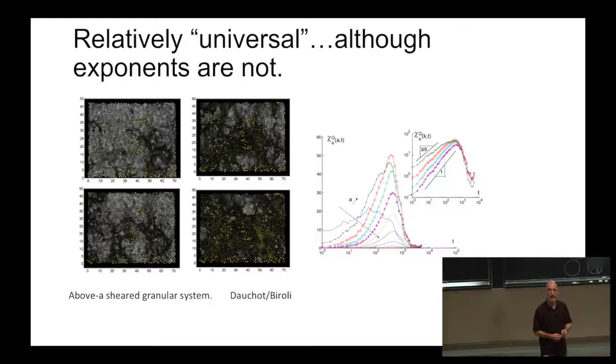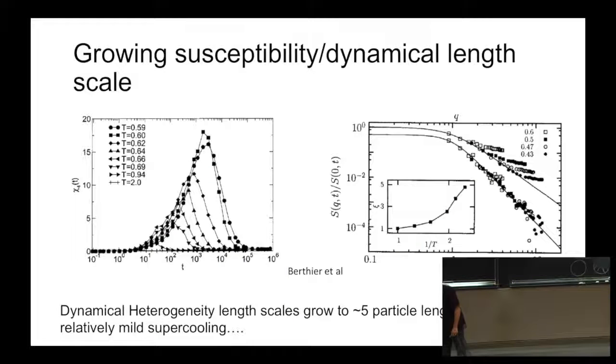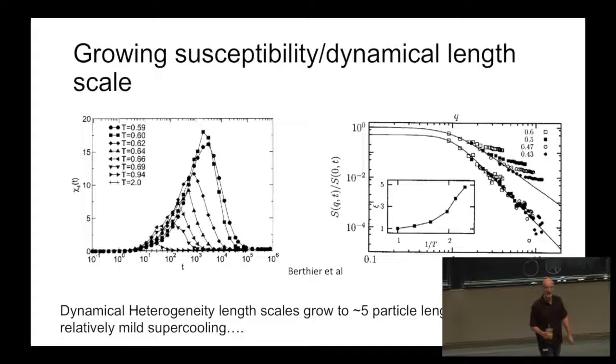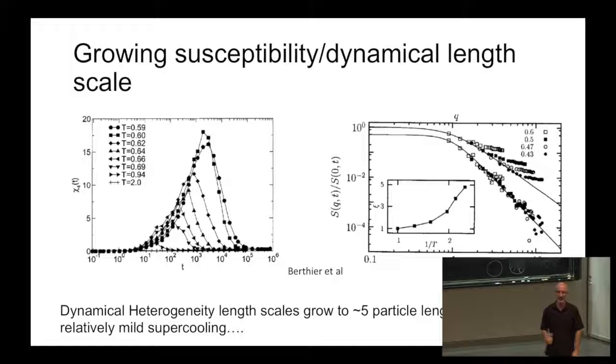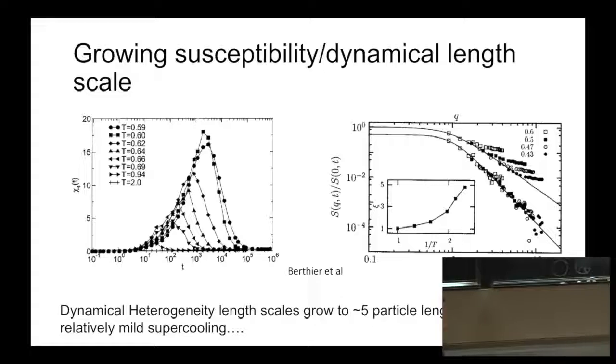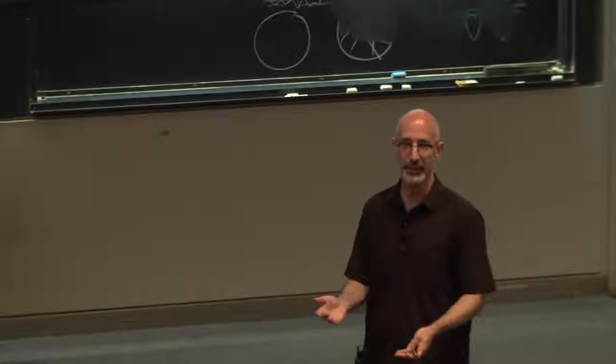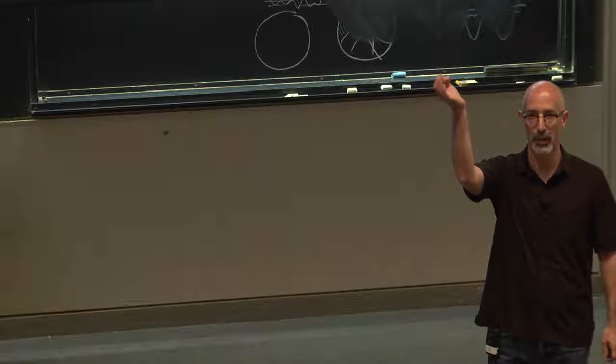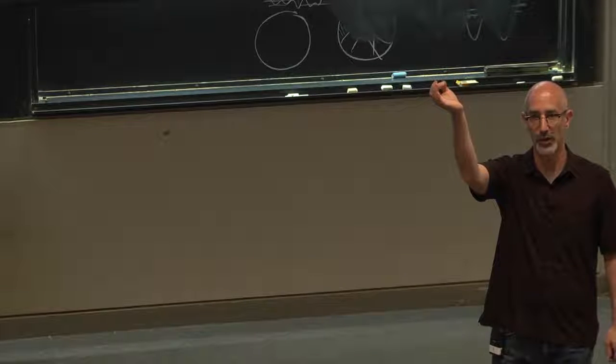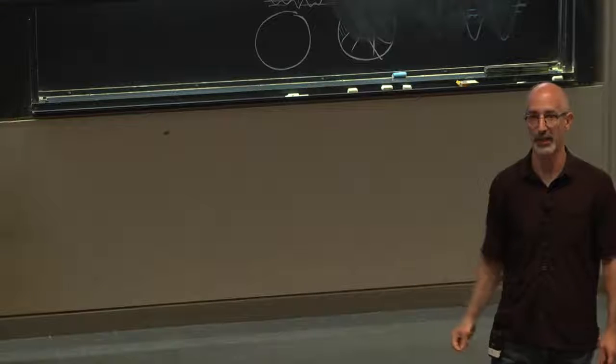On the last slide, you mentioned that you're looking at a length scale of something like 5 particle lengths, but that you need to simulate a system of 100,000 particles to see it. It's not that you need 100,000 particles to see the length scale, but part of it is that it's not really clear what the right scaling form is that you want to fit your data to. That goes back to Giorgio's point. If you do 1,000 particle simulations, you're limited to the lowest wave vector you can go to; below that it doesn't mean anything because of the periodic boundary conditions of the system.